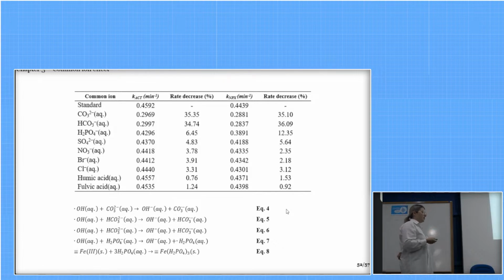Now that we have optimized the process, we wanted to confirm its environmental applicability. So we studied the common ion effect, where we tested for various ions present in the environment, and we observed a rate decrease of approximately 35% for the formation of basic salts, where we see that there is a possibility for OH radical being converted to radical species of these salts, these carbonate salts, which have decreased oxidative potential. And we also saw that there is a possibility for these other salts to interact with the surface of the iron of the catalyst, forming a sort of complex precipitate.